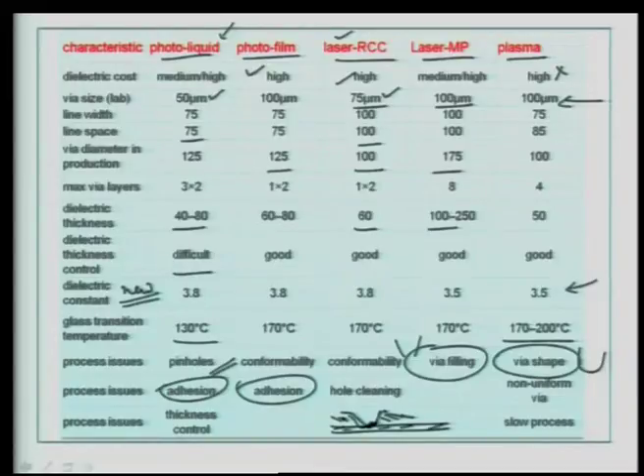So, the key to getting high yield and sustaining during the thermal cycling the natural life of the product is that these microvias should be defect free during its operation, and the plating that happens and the electroless copper to dielectric adhesion is also a very key issue. And if you are doing laser drilling, again because it is an ablative process, you have to make sure that you clean the hole walls fairly well, just like in your conventional MLB process before your electroless plating. So, thickness control, adhesion and being defect free are some of the key issues that one has to be aware